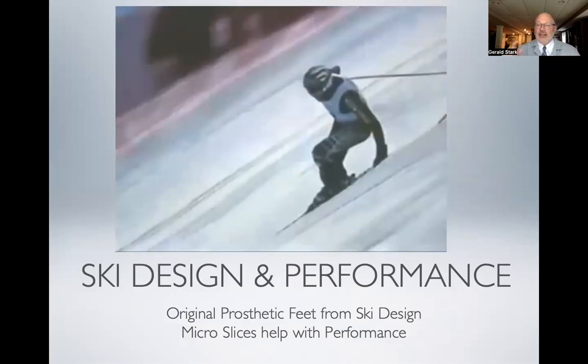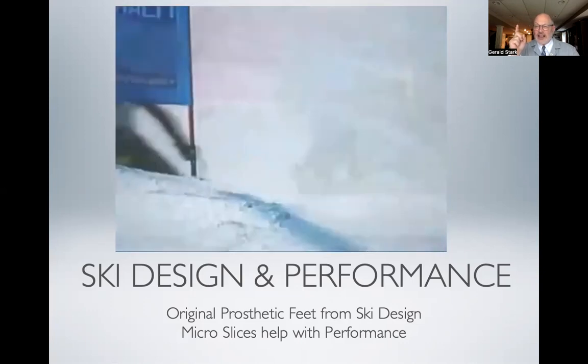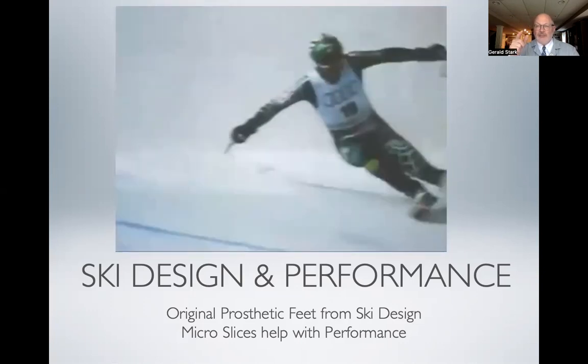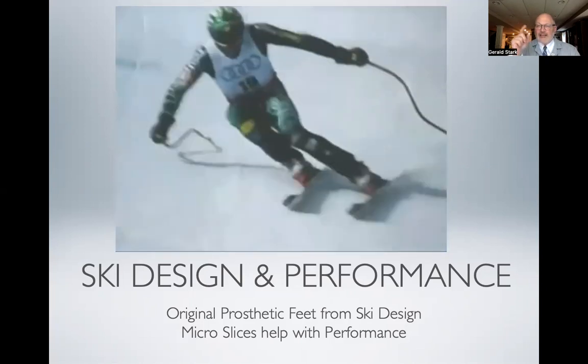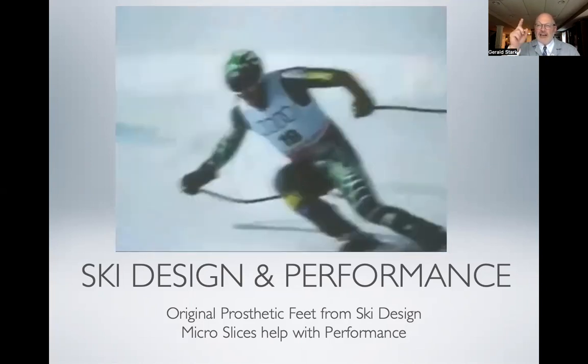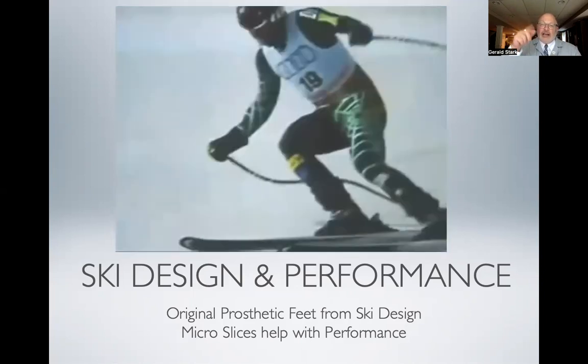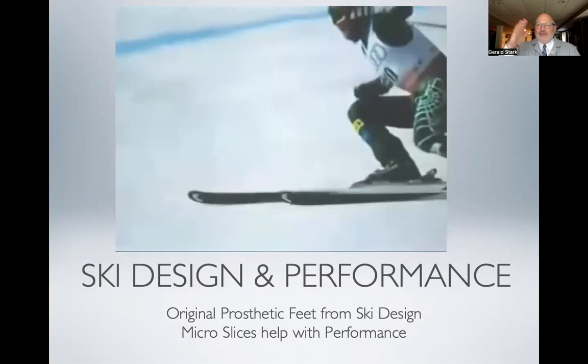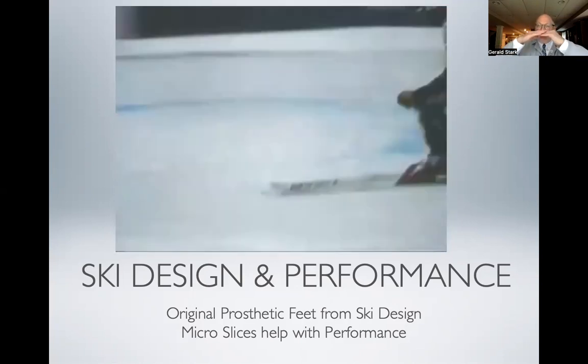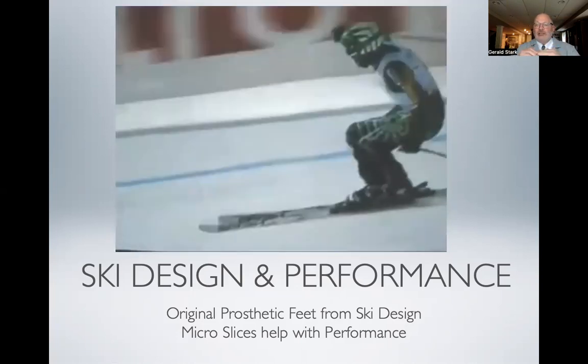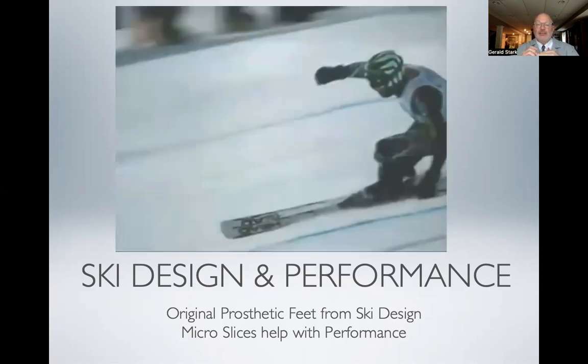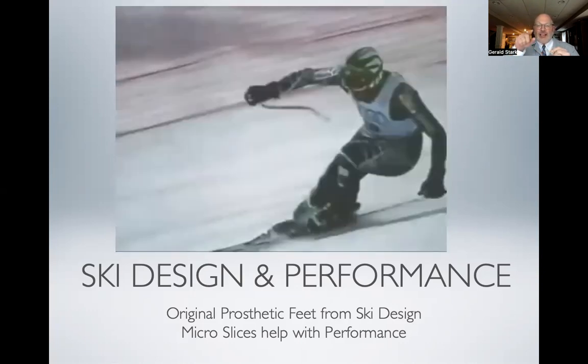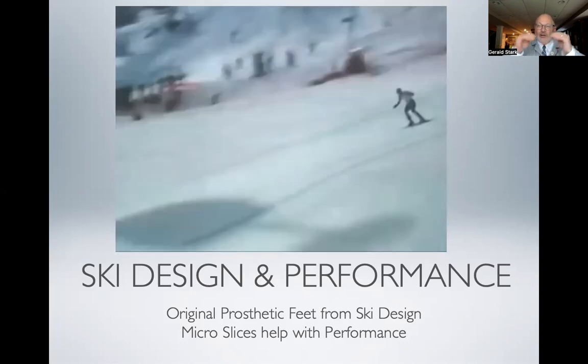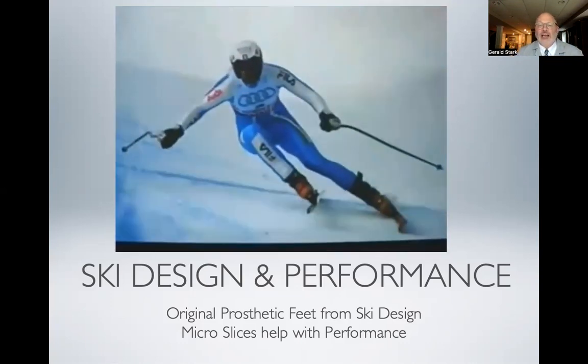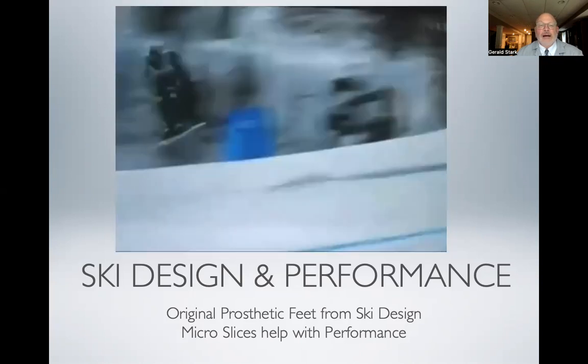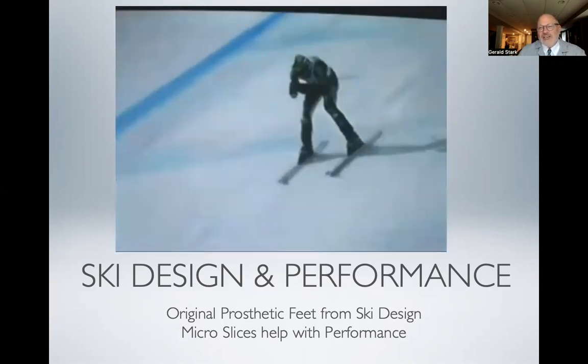The modulus, or the distance that the device deflects based on load, is very similar to aluminum. But here's the thing, carbon can be flexed quite a bit more over an infinite amount of time, and it'll come back typically. Now, there usually is a difference with carbon fiber. As those little micro adhesions with the resin flex, it'll change its stiffness over time. So that's one of the differences. And you can see little micro slices sometimes could help change the variable stiffness. You can see just how much strain is being put on those two little carbon skis. When you think about it, it's really a quarter of an inch that's riding on the edges.